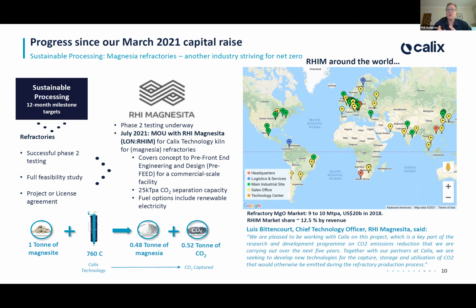Our facility at Bacchus Marsh is already at this scale, so there's no scale-up risk required with respect to this particular project. The key thing that we're doing is testing to make sure that the magnesia that we produce out of our kiln is suitable for then on manufacturing into the refractory bricks that companies like RHI Magnesita make. And so that testing's been going on for quite some time, and phase 1 has passed and was very successful.